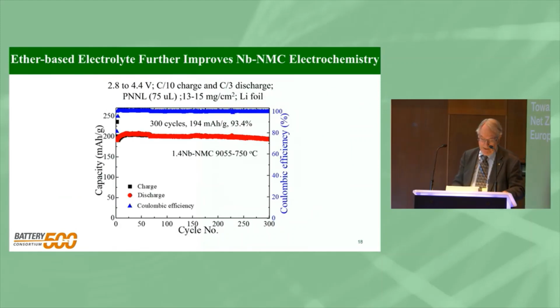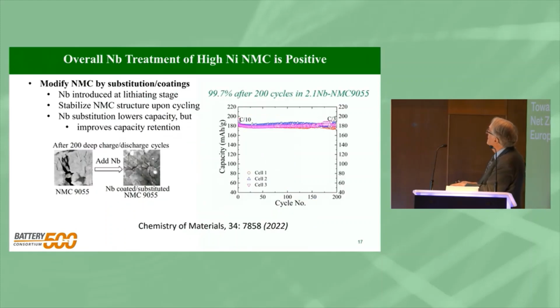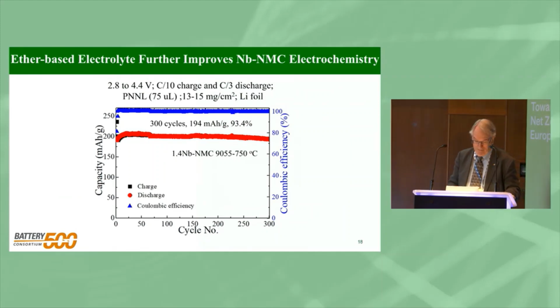But what we did, and let's go back to this one from there. This is a standard electrolyte formulation. We've got lithium metal. We've got the standard commercial carbonate-based electrolyte with LiPF6 in it. We've switched over to what we call our improved electrolyte. This is the one developed by Pacific Northwest National Lab. They went back almost 50 years, and said, let's go back to the ethers, which is what Exxon used. Ethers plate out lithium much better than carbonates do.